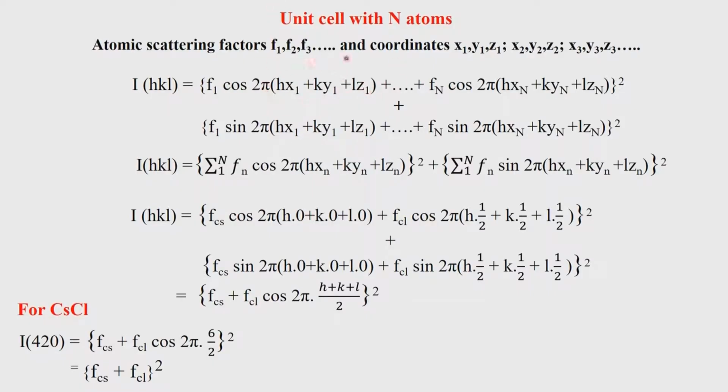Since we do not know where xyz is, the modulus value which we get for the structure factor is devoid of phases. No experimental way is available with the way we do the experiment. No experimental approach can be developed to find the phase. So therefore, we have to determine or guess the phases that are associated with the structure factors. So you might ask a question, why not use the intensities and do a Fourier transform? What happens if we do the Fourier transform of intensities?